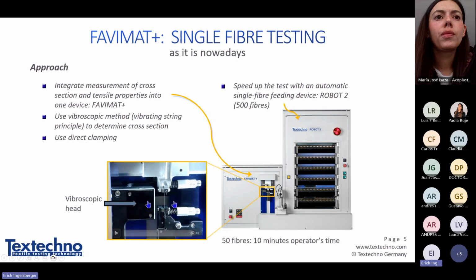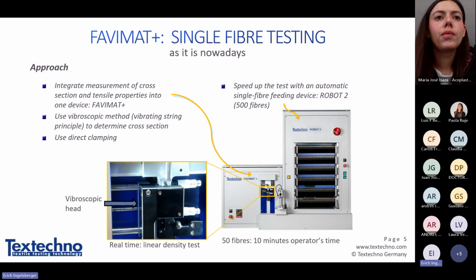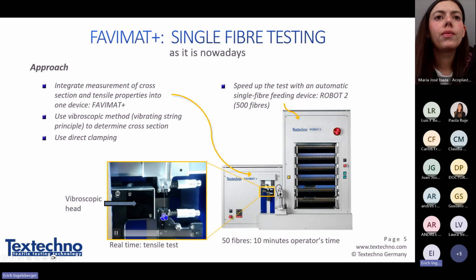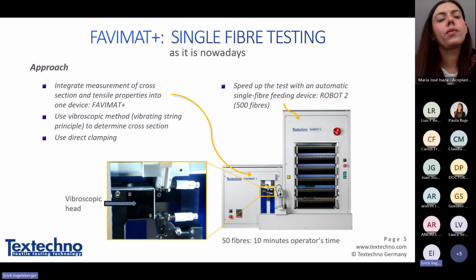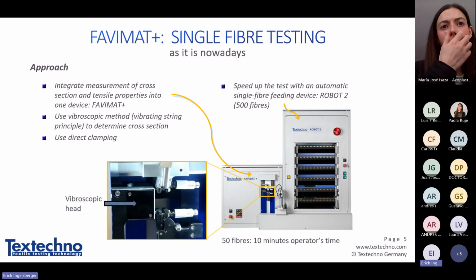This measuring head moves over the fiber to excite it by a speaker to find the resonance frequency. After finding the resonance frequency, it will start a tensile test. So you can see the lower clamp here moves down to break the fiber. Of course, this is not a carbon fiber, you would not be able to see a carbon fiber, so I show a picture of a standard polyester fiber just to make it clear what the instrument is doing. But of course, it works with carbon as well.